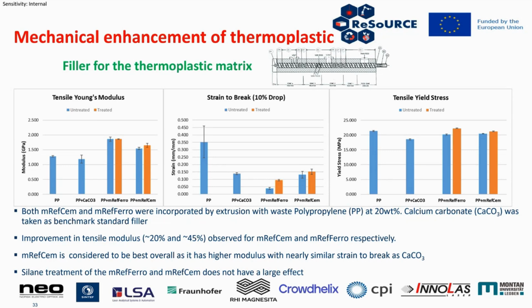So there is an improvement. There's also a little bit of a drawback there. Before, I mentioned that we can coat these with silanes to surface modify them. So we modified this with a silane specifically for polypropylene, which is the right-hand graph there. What you can see is the coating with the silane in this instance didn't give us large benefits to the modulus. So for this application, you would not need to coat the particles. You could just use them as the milled material itself.